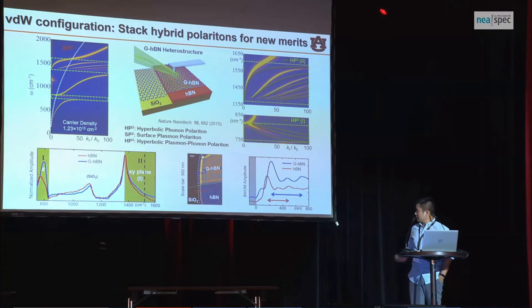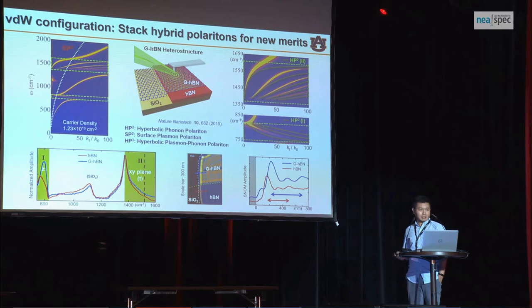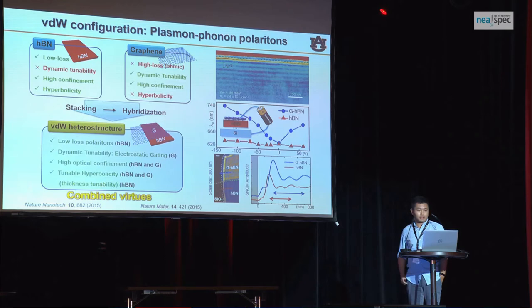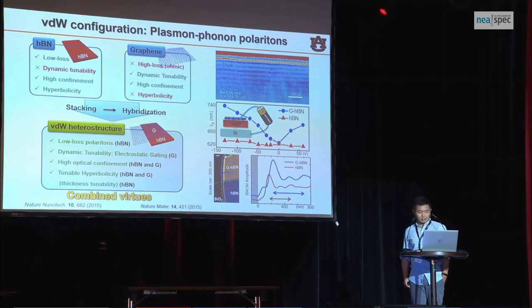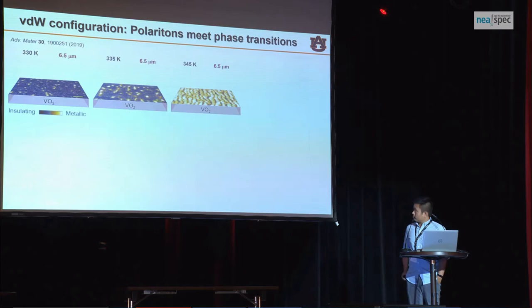As shown in this device, a single layer of graphene actually elongates the wavelength of phonon polaritons in boron nitride by about 50%. To summarize the results: combining graphene and boron nitride, you can achieve tunability — dynamic tunability — of phonon polaritons, and also elongate the propagation length in this hybrid system.